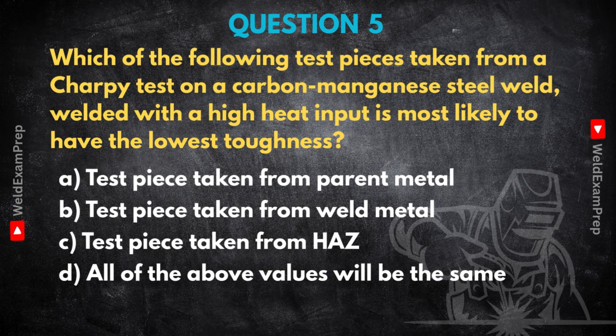Okay, this is a really important one in practice. The area most likely to have the lowest toughness in this situation is C, test piece taken from the HAZ, the heat-affected zone. The HAZ. Why specifically the HAZ with high heat input? Well, when you weld carbon manganese steel using high heat input, you're pumping a lot of energy in over a longer time. This means the HAZ, the metal right next to the weld, gets very hot for quite a while, and then it cools down relatively slowly.